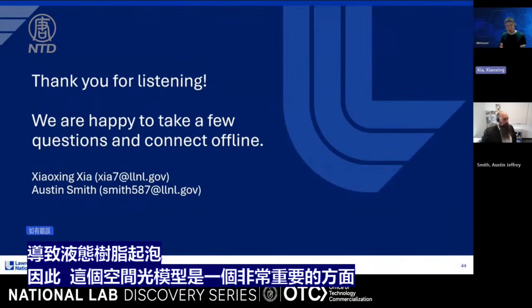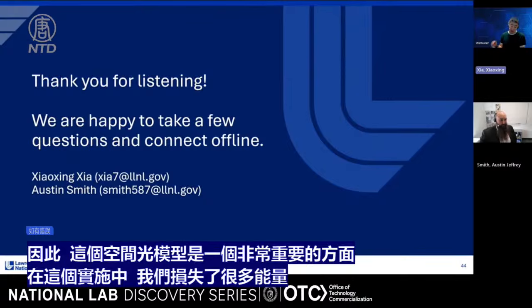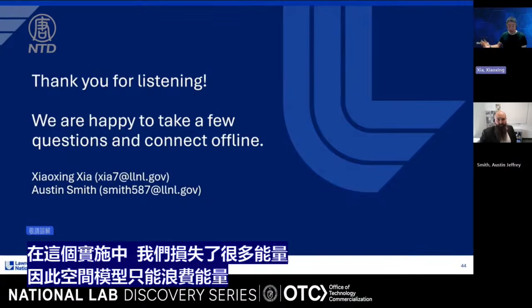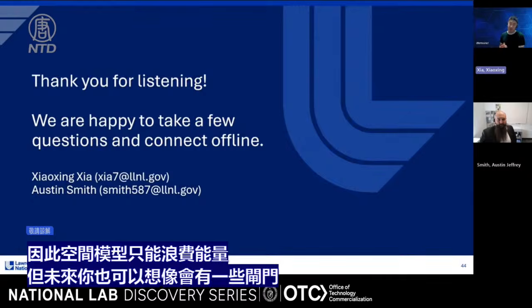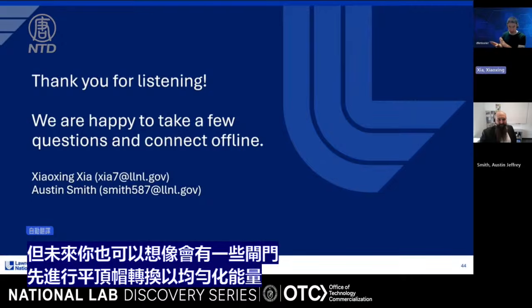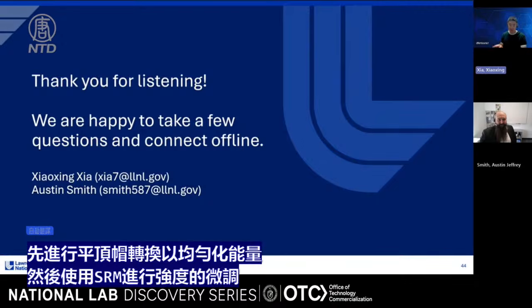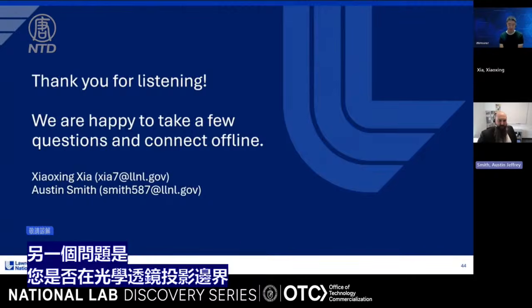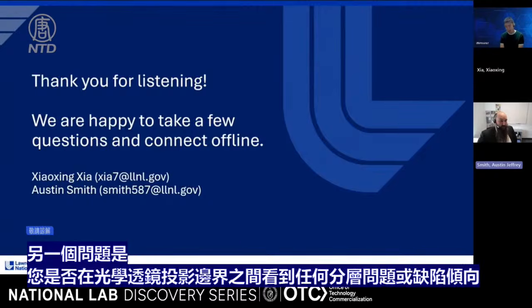In this implementation, we lose a lot of energy, so the SLM can only throw away energy. But in the future, you can also imagine having some flat-top conversion to levelize the energy first, and then use the SLM to do some fine tuning of the intensity. Great. Another question here. Do you see any delamination issues or defect tendency along the edges between metalens projection boundaries?